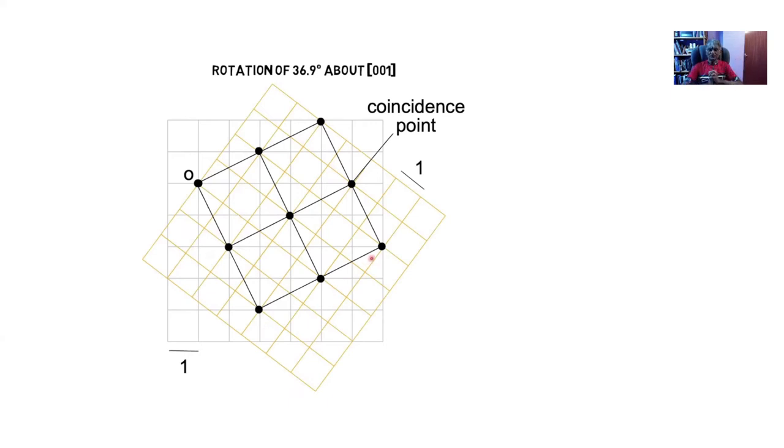Right, now, if we look at what happens at these sites, I've already given you a clue that if we have a high density of coincidence points, then the interface energy is likely to be low, and there's a bit of terminology that since one fifth of the lattice points are common to both of these lattices, we say capital sigma equals 5.